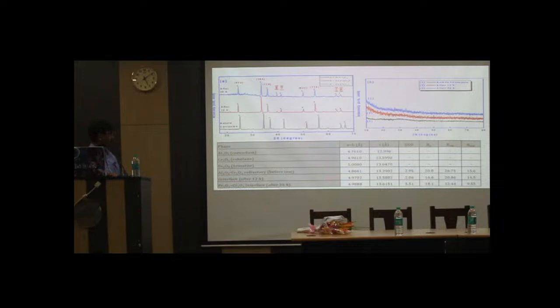After 12 hours, it is 4.97, and this eskolaite, pure Cr2O3, is 4.96. So after 12 hours, it is just near the eskolaite phase. But after 36 hours, 4.988, so it crossed the eskolaite lattice parameter and moves towards the iron oxide. That clearly indicates that iron oxide enters into the structure, and it ultimately forms the iron and Cr2O3 type of solid solution, and this actually ceases the corrosion rate.